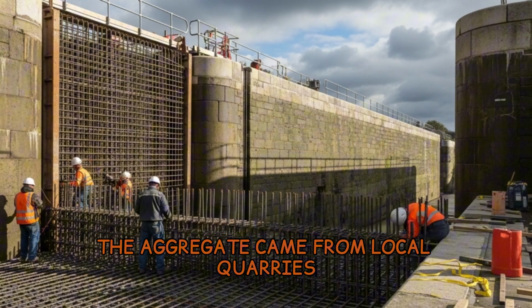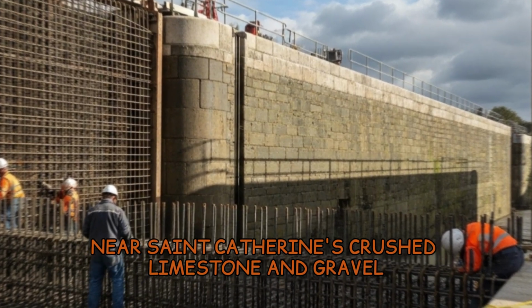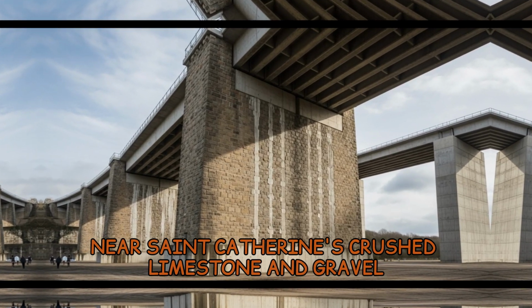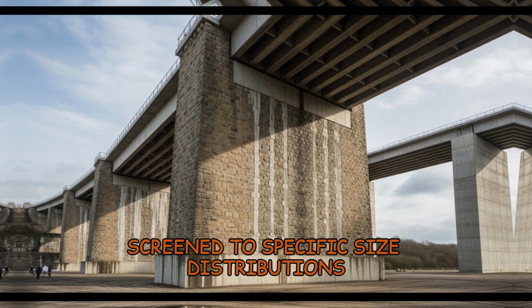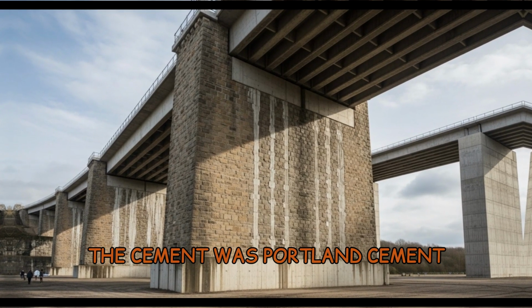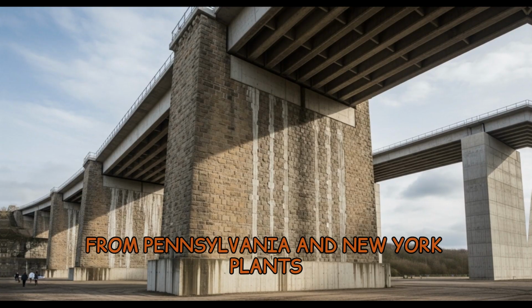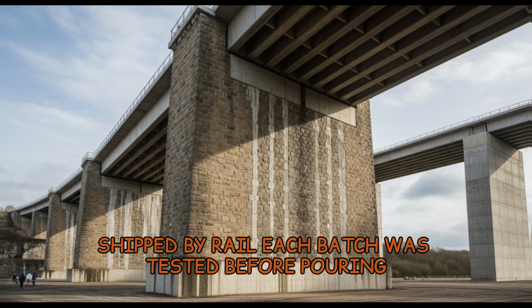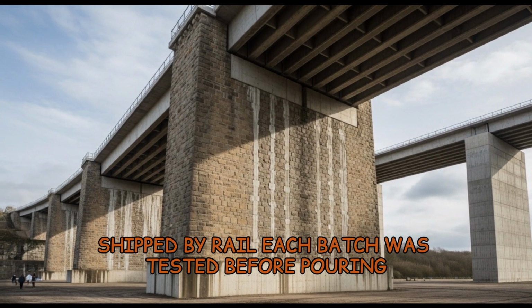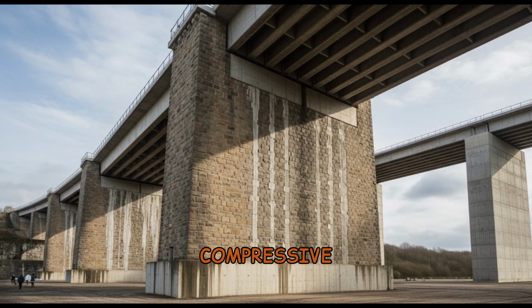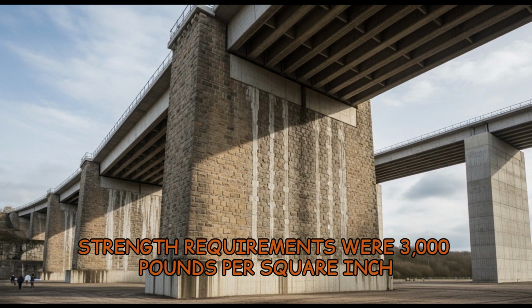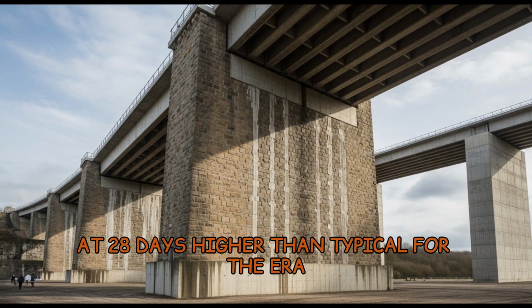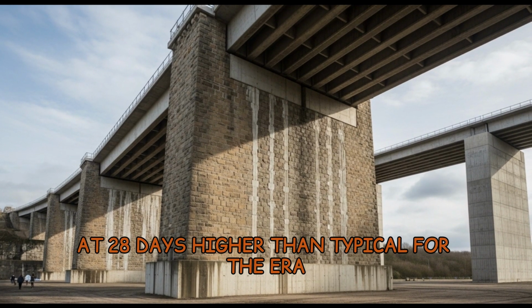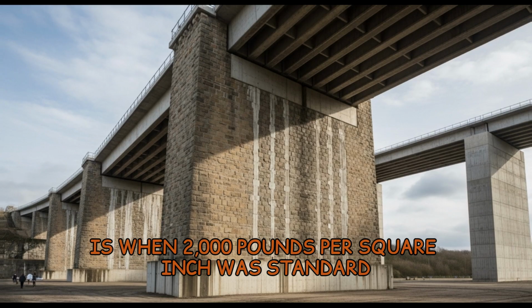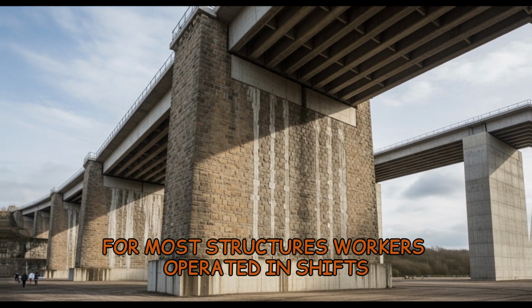The aggregate came from local quarries near St. Catharines. Crushed limestone and gravel, screened to specific size distributions. The cement was Portland cement from Pennsylvania and New York plants, shipped by rail. Each batch was tested before pouring. Compressive strength requirements were 3,000 pounds per square inch at 28 days, higher than typical for the era, when 2,000 pounds per square inch was standard for most structures.